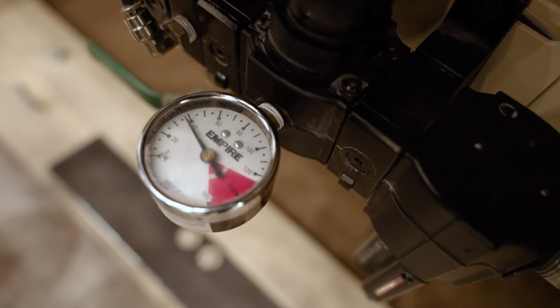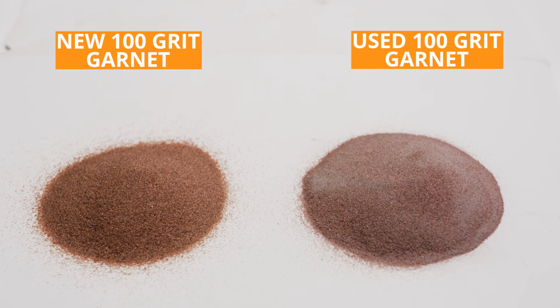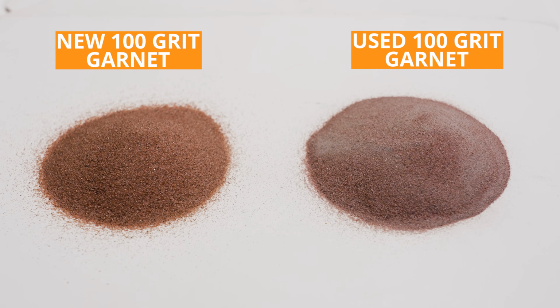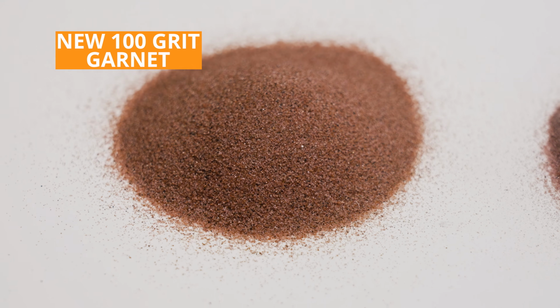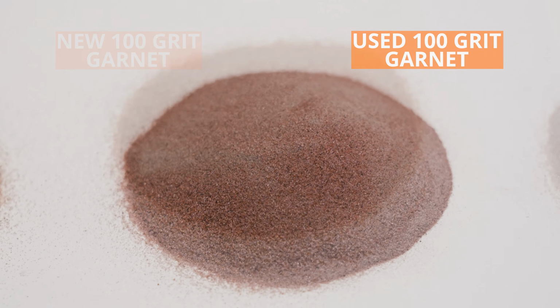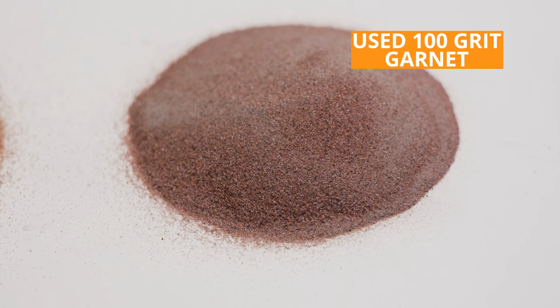I hear it a lot. My Cerakote job chips or flakes. Normally it comes down to not blasting at the right pressure, not blasting with the right grit size of media, or blasting with rundown, ragged media that maybe at one point it was 100 grit. But it's been in the cabinet for so long and been blasted on so hard that it's now actually 120, 180 grit.